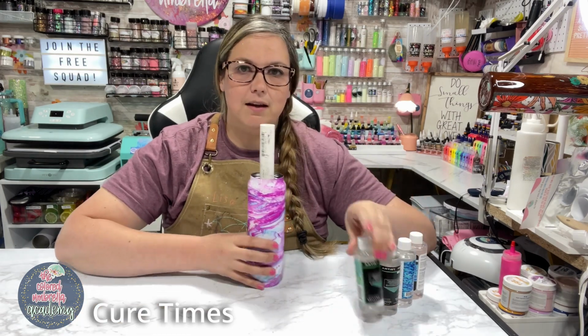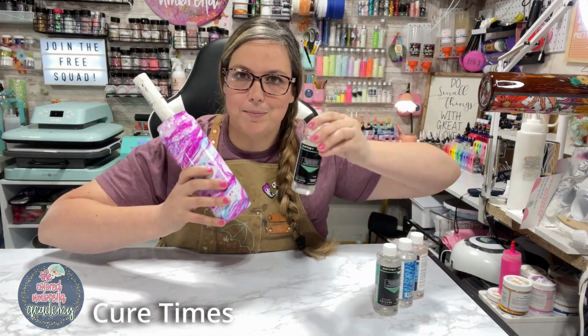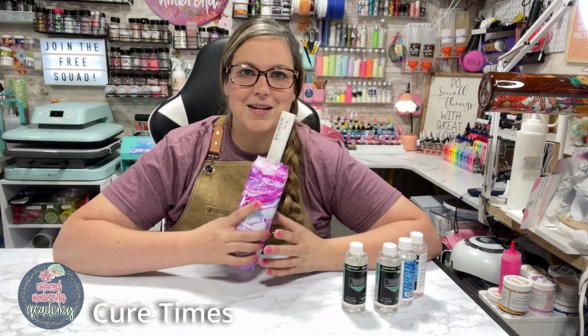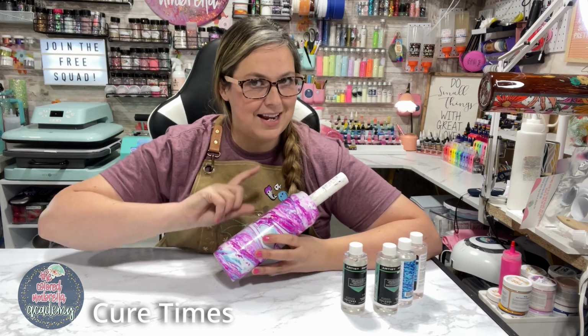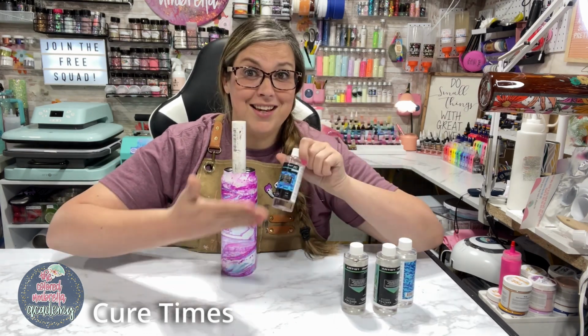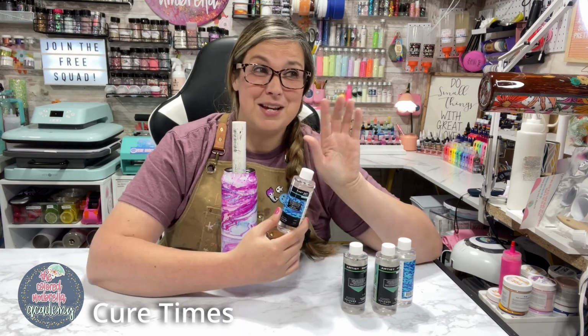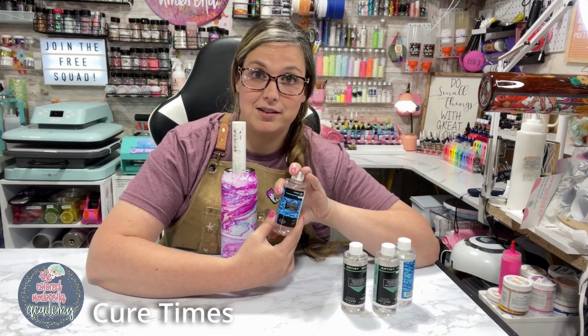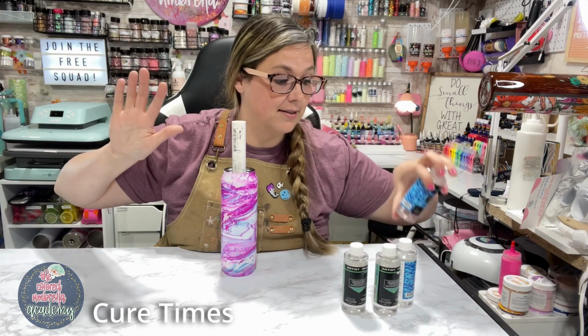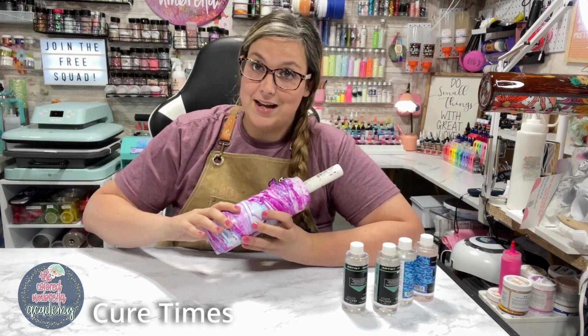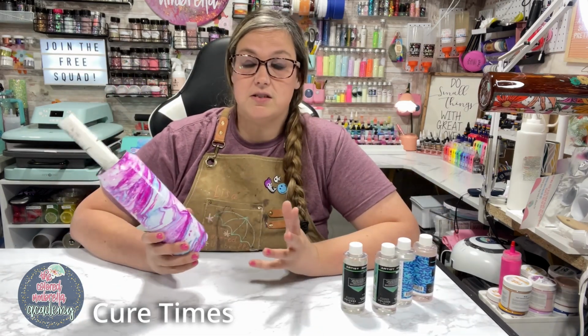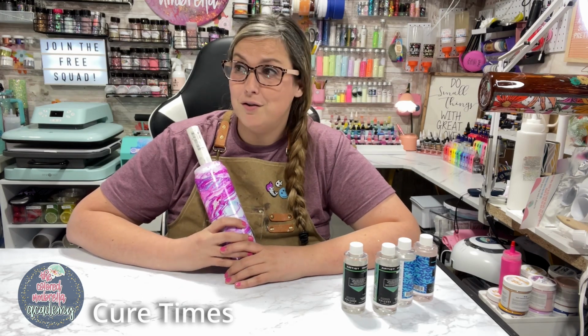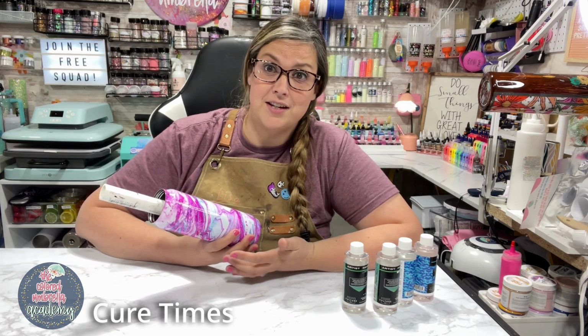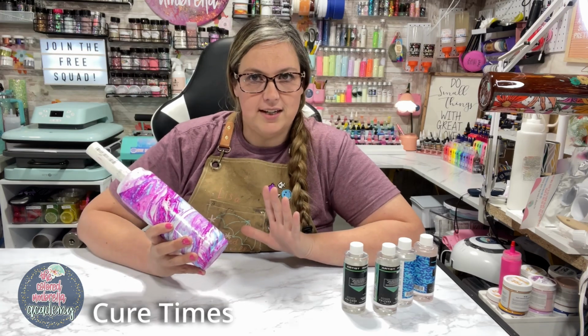Well, if you're using a regular artist resin epoxy, your cure to the touch time is going to be about 8 to 12 hours. If you're using a fast setting epoxy, it'd be about 90 minutes to 2 hours. Again, depending on your environment. The warmer your room is, the faster it's going to cure. So it really all depends. In the summertime, you're going to notice that your tumblers cure a lot faster than they do in the wintertime. Always make sure you're adjusting accordingly.